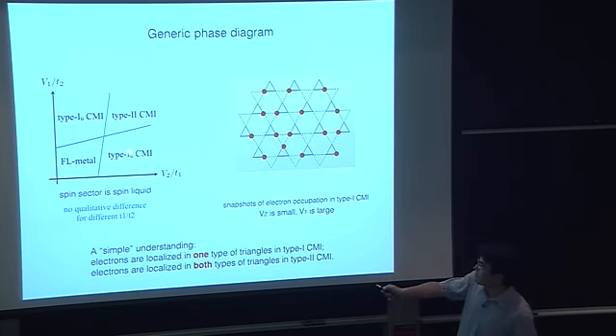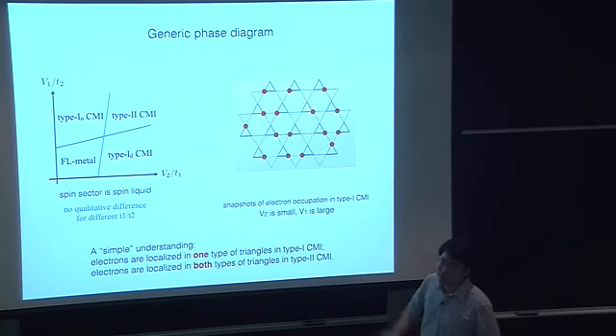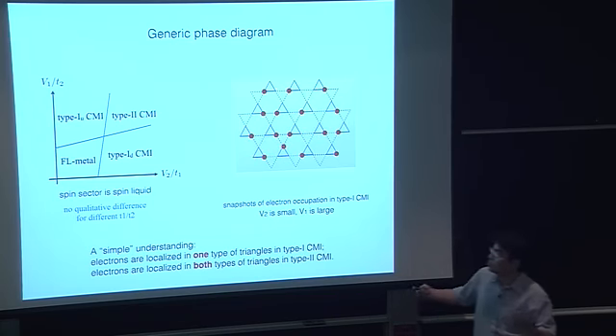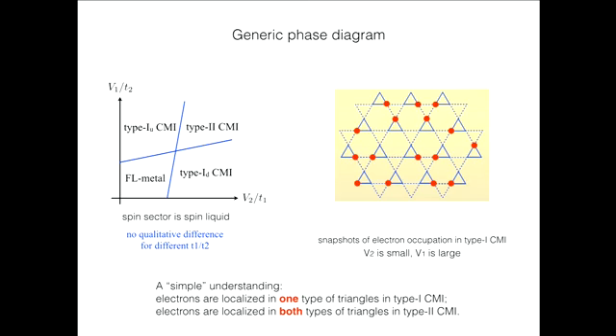Similarly, if I increase V2 but keep V1 small, the electron will localize on the down triangle. This is type 1 down. Suppose I increase both V1 and V2, making both of them large. Then the electron should be localized on both up and down triangles. The electron number on both up and down triangles will be fixed to be 1. So a simple understanding is that electrons are localized in one type of triangle in a type 1 cluster Mott insulator, and electrons are localized in both types of triangle in a type 2 cluster Mott insulator.